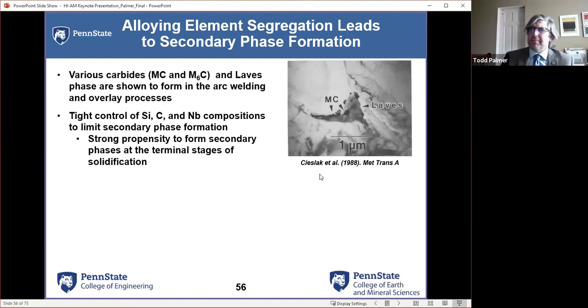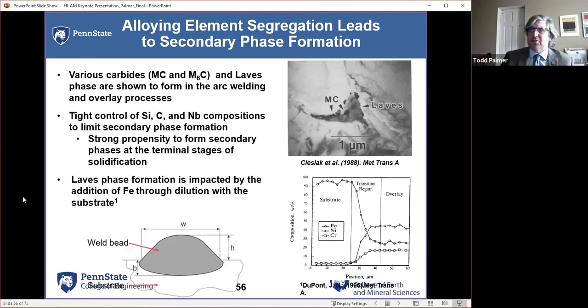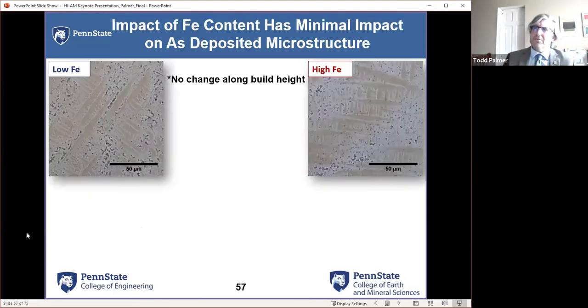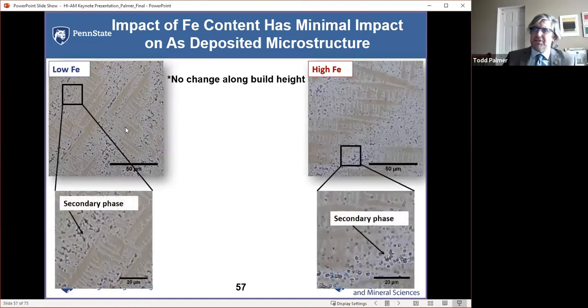And so they really came on, this is Mike Cieslak back in even the late 80s, of looking at, we need to control silicon, carbon, and niobium to limit this secondary phase, because there's this propensity to form these phases. And so they really were tying into the formation of Laves phase with the addition of iron. And that was typically done through overlays and really the dilution of the iron from the underlying substrate into the Inconel. And so high iron was really traditionally linked to this idea that I'm going to form a lot of Laves phase. Now, we sort of did the same type of thing. What we started to see in our microstructures, and these are some as deposited ones, is really these second phases. Didn't really change that much, but we had them.